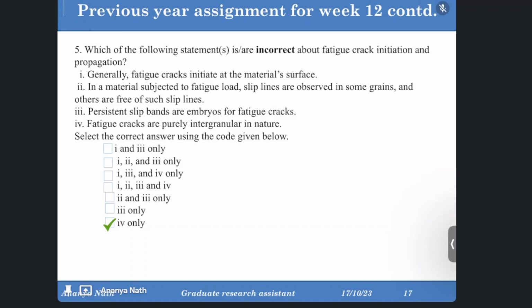In metal subjected to fatigue load, slip lines are observed in some grains. Obviously, they will not be present throughout the grains, because even alloys and composites have localized deformation. So obviously slip lines will be observed in some of the grains, while others are free of such slip lines, and the persistent slip band will act as an embryo for the fatigue crack.